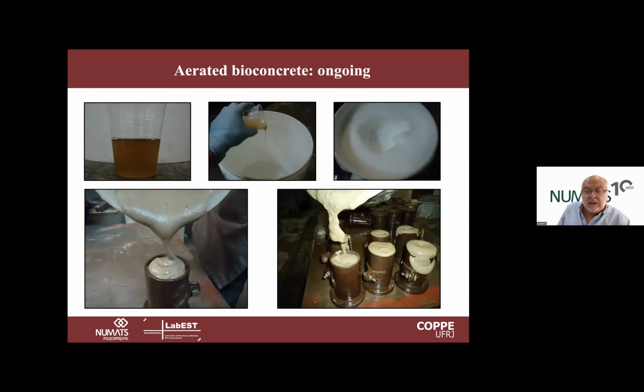We are now studying the use of ultralight materials. So the density here is in the range of 100 to 120 kilograms per cubic meter. Then in this case, these materials can be used as insulators and also to produce a sandwich system using outer layers with textile or short fiber reinforced cement matrix as well. So we can produce sandwich panels and then develop construction systems using these materials.